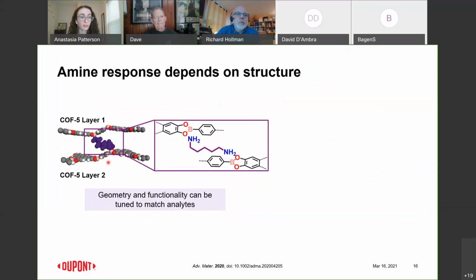If we do DFT simulations to look at the actual interlayer structure of these assembled materials, you can see that cadaverine actually fits exactly in this spot between these two boron groups. So there's a strong interaction at this end and at this end. That combination of strong chemical interaction, as well as being bidentate with two points of contact, really highlights how both the geometry and the chemical functionality can be tuned to match some target analyte. In this case, if you really wanted to sense cadaverine, this would be a great material.